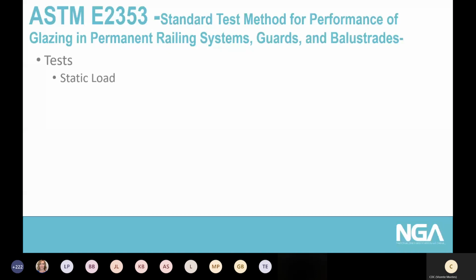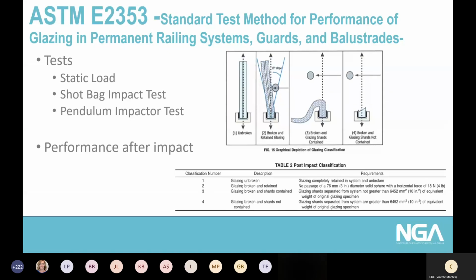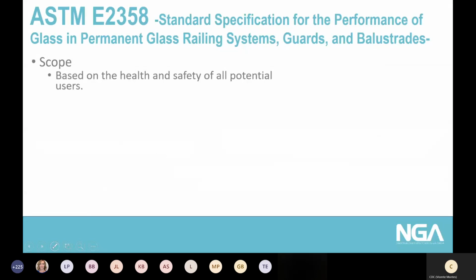Now, let's go to ASTM E2353. This is the standard test method for performance of glazing in permanent railing systems, guards, and balustrades. There are 3 different types of tests per this ASTM: the static load test, the shot-bag impact test, and the pendulum impactor test. Now, there are 4 different classifications per this ASTM. But if you remember the section that we just emphasized, that the glass after the impact needs to remain as a guard, that means that per that code requirement, Classification 3 and Classification 4 would not meet that requirement. So we're looking at Classification 1 or 2 to be able to meet the IBC.